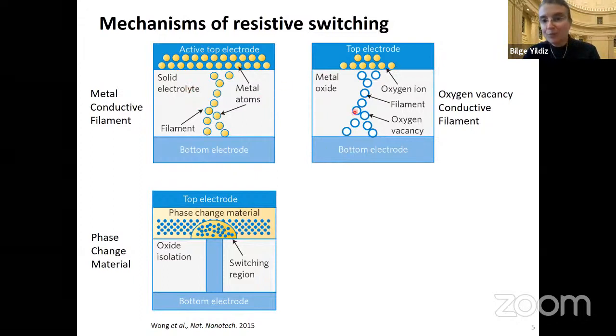A similar process is conductive filament formation, but instead of metal, we are now working with oxygen vacancies. So the medium is an insulating metal oxide, and again, electrically, or rather electrochemically, you can create oxygen vacancies in this insulating oxide, and they form again a filament or a dendrite that is rich in electronic conduction around them and forms the electronically conducting filament. So metal filament or oxygen vacancy filament.